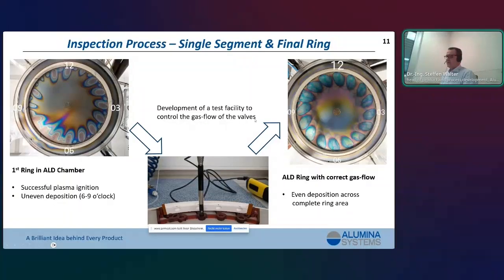And so we said, okay, we have to get more into the control of such ring structures, and we developed a test facility to first control the gas flow of the valves. So what we see here in the middle picture is a very smart, very small test facility with a gas flow meter. And here we control all the valves and check if the gas flow is absolutely correct.